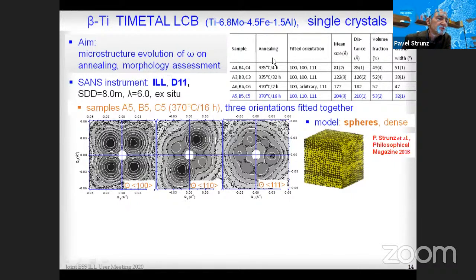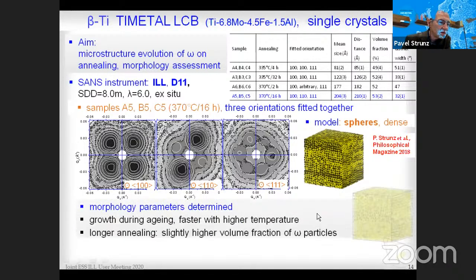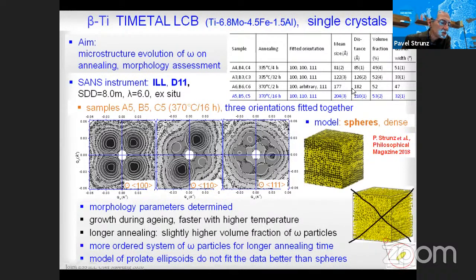So we had a series of differently annealed samples, which were cut along three crystallographic planes. In these graphs, the grayscale means measured data, and the white equi-intensity levels are the fit to the data using this three-dimensional model of dense spheres, which represent omega precipitates. When we evaluate all the data, we determine some morphological parameters. Well, there is nothing very special for the size and volume fraction.